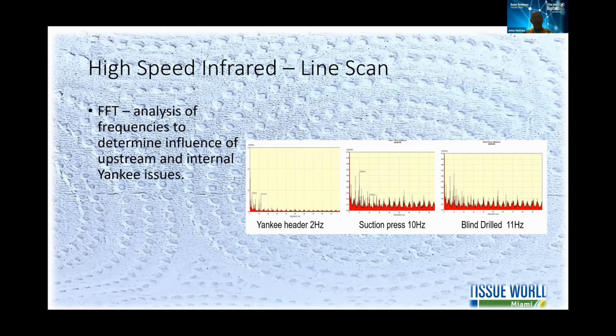Each pixel in the high-speed line scanning can be used to develop an FFT analysis. So you can use the frequencies to determine any influence upstream or internal issues. So it could be a condensate system inside the Yankee. However, if the FFT shows a longer or a lower frequency, it might be the felt. And the line scanning can also pick up seams in felts, for example.